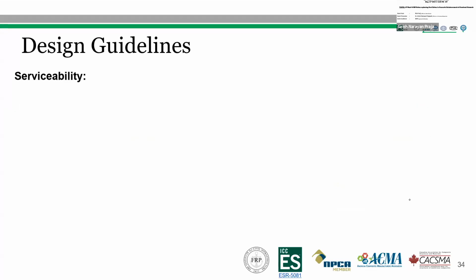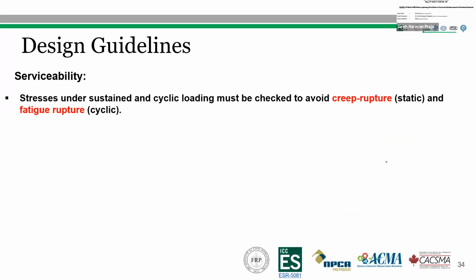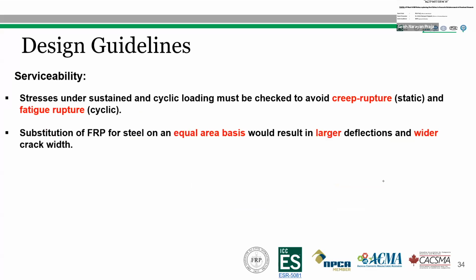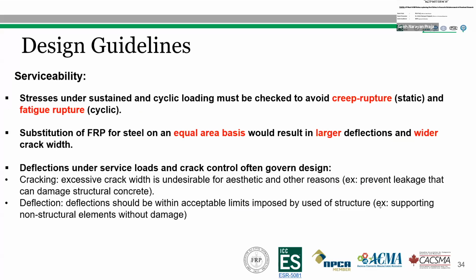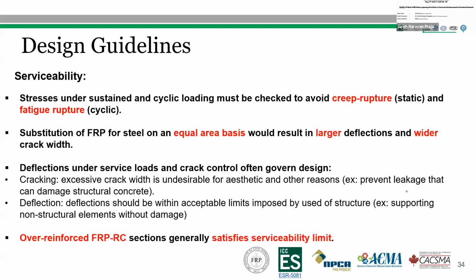The following serviceability criteria are required. The stress under sustained and cyclic loading should be checked to avoid creep rupture and fatigue rupture. The substitution of FRP bar for steel bar on an equal area basis would result in large deflection and wider crack width. The design is governed by deflection under service load and crack control. The excessive crack is undesirable for aesthetic and other reasons, and deflection should be within the acceptable limit to support non-structural elements. Over-reinforced or compression control sections typically satisfy the serviceability limit for the FRP reinforced concrete section.